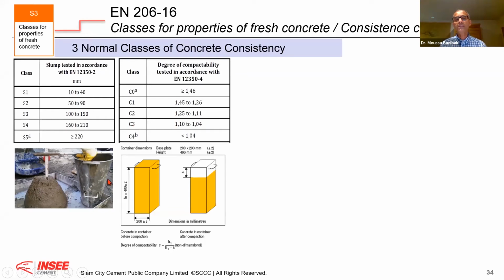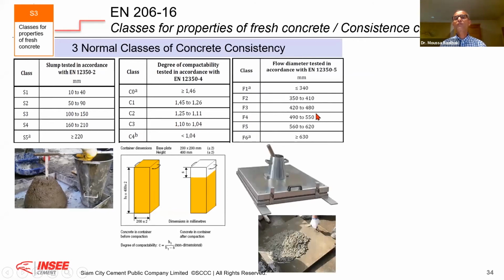It's normal. If I place this concrete, I compact it and it's not slumpy, it means already the concrete has high compactability. And also there is what we call the flow diameter. Sometimes in Sri Lanka, we use it, but we don't use the right cone. We use this cone to take the flow. Normally the cone you use for the F class, the flow diameter is smaller. This is the DIN cone. It's not the Abrams cone, it's a DIN cone. Therefore it's different. Therefore you lift the cone and you compact. You give a tap, 15 taps here, and therefore you measure the diameter.